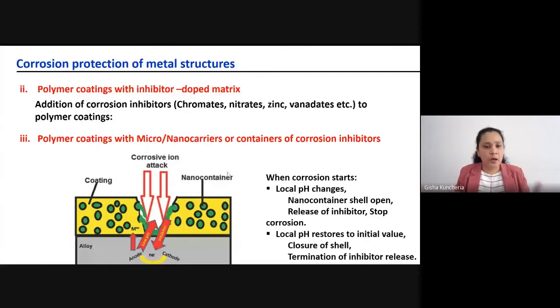Another technique, very commonly used in the oil and gas sectors, is to mix the polymer coatings with corrosion inhibitors like chromates, nitrates, zinc or vanadates. All these are good. But another drawback is that these corrosion inhibitors will react with the polymer coatings and destroy the integrity of the coating. Or these corrosion inhibitors leach out from the coatings and cause environmental problems, especially these chromates. Chromates are very good inhibitors, but they are carcinogenic.